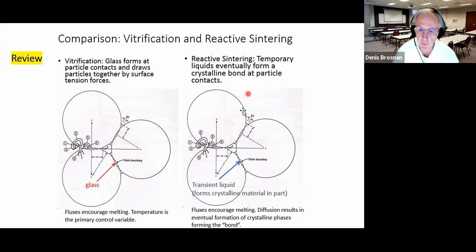Now, in reactive sintering, we also have a glass phase that forms between particle contacts, and then that glass phase further reacts with other substances there, maybe the major aggregates, to create a second crystalline phase. Glass phase may be there. Glass phase may be transient in nature, meaning it can go away after the product has reached its maturity. But nevertheless, we're going to have a reactive sintering situation with a major mineral, in this case being corundum, and a minor mineral, in this case being mullite, and perhaps a little bit of glass that's present.